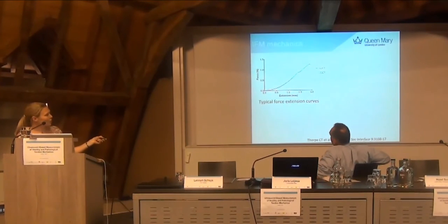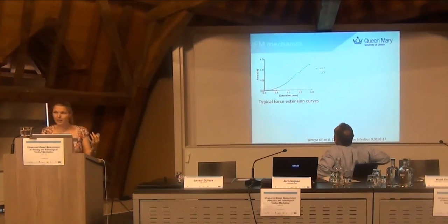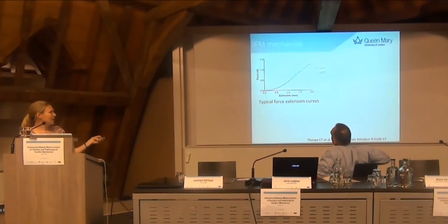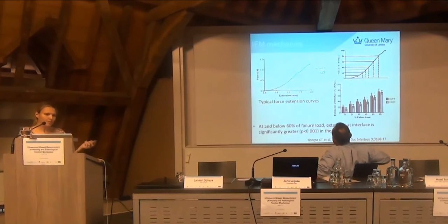Here is our energy store. Look at this lower stiffness region. Remember in the energy storing tendon we needed the fascicles to slide more to allow the tendon to stretch more? Rather nicely, we see this nice low stiffness behaviour that would allow that sliding to occur more easily. And that's an example curve. Here's the data over all of them.